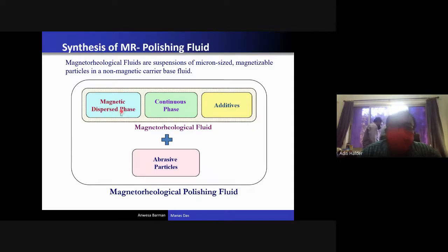So for these iron particles we are mostly using carbonyl iron particles, Fe(CO)5. These carbonyl iron particles are supplied to us by BASF. BASF is a very famous chemical company in Germany. They prepare these carbonyl iron particles, and they gave them to us free of cost. The density of these iron particles is 7.81 gram per centimeter cube, which is around 7 to 8 times higher than the water-based or oil-based media. So there is a sedimentation problem in the container where we are mixing the media.